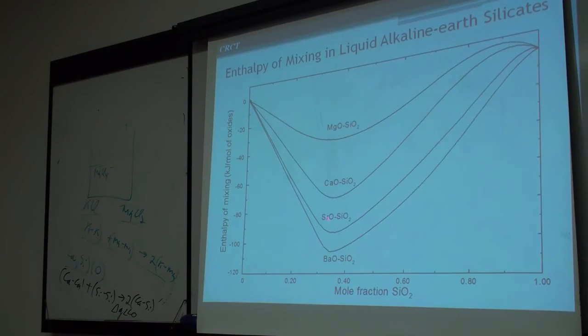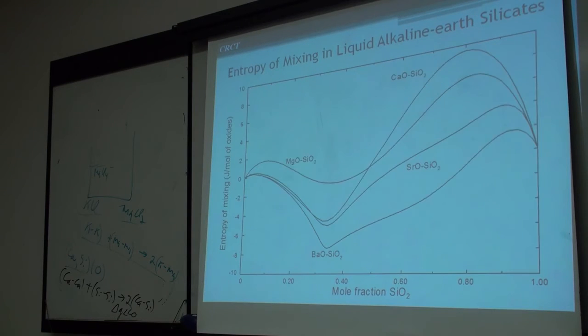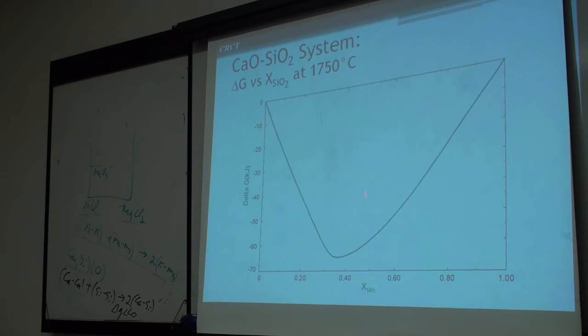All right, but over here you notice this thing comes down very negative, and then you get this positive flip up here. It tends to curve around like that. You can see that here very, very slightly. You see a positive flip. If you put a ruler along here, you'll see that you're going to get a miscibility gap on that side. A very strong negative to form the complex, and then it tends to become somewhat positive over here.